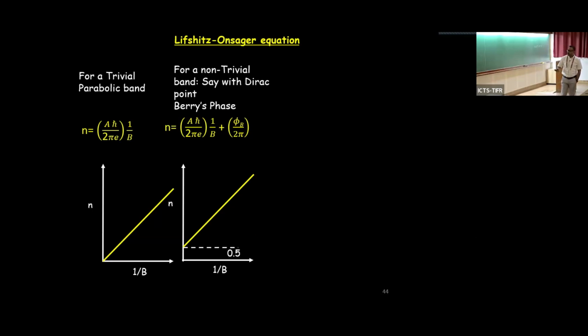Then the Landau index plot should not go to the origin, but it should go to 0.5, and this 0.5 gives rise to a pi Berry phase in the system, and that signifies that your band structure is a non-trivial band structure. But in both cases, this should be linear as a function of 1 over B.